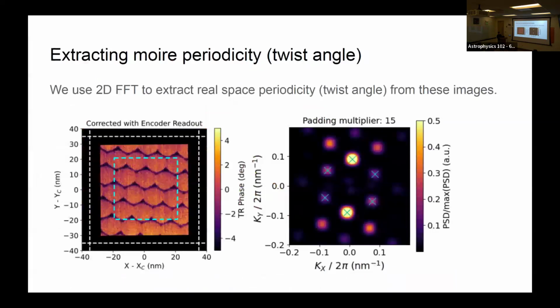So how can we extract the spatial information or periodicity from these images? The simplest thing is to use a 2D Fourier transform and look at the Fourier peaks. By using the magnitude of the Fourier peaks, we can back calculate the wavelengths of the moiré. You could, in principle, also work in real space, applying some signal-to-noise treatment to extract the periodicity from the real space image.